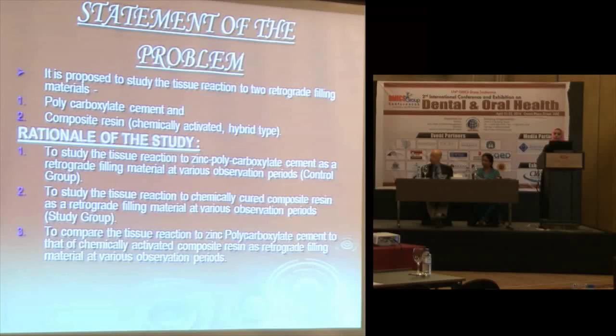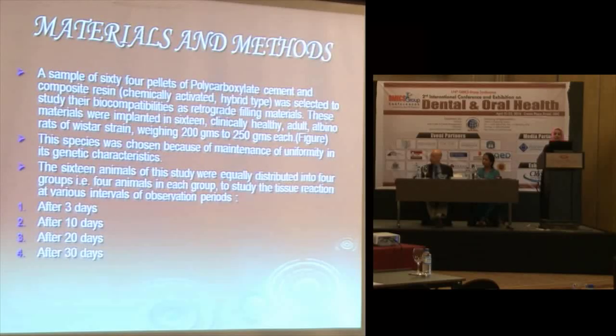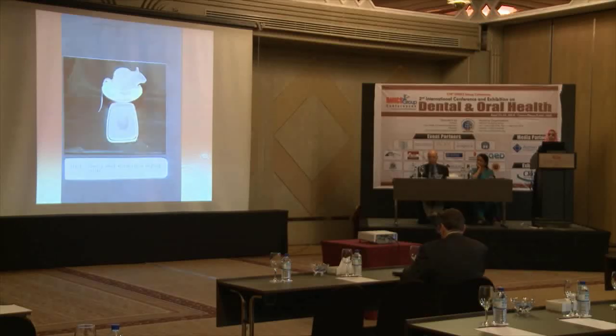And then to compare the tissue reaction to zinc polycarboxylate cement to that of chemically activated composite resin at various observation periods. A sample of 64 pellets of polycarboxylate cement and composite resin was selected to study the biocompatibilities as retrograde filling materials. These materials were implanted in 16 clinically healthy adult albino rats of Wistar strain weighing 200 to 250 grams. This species was chosen because of maintenance of uniformity in its genetic characteristics. The 16 animals of this study were equally distributed into 4 groups, that is 4 animals in each group, to study the tissue reaction at various observation periods, after 3 days, 10 days, 20 days and 30 days. This shows the albino rat on the weighing scale.